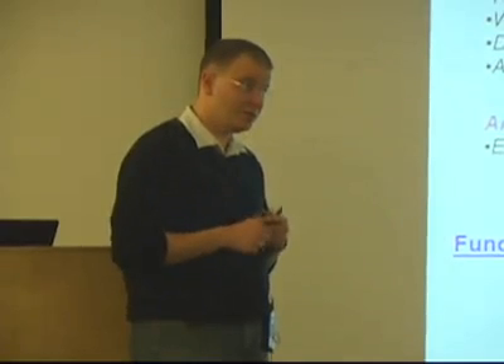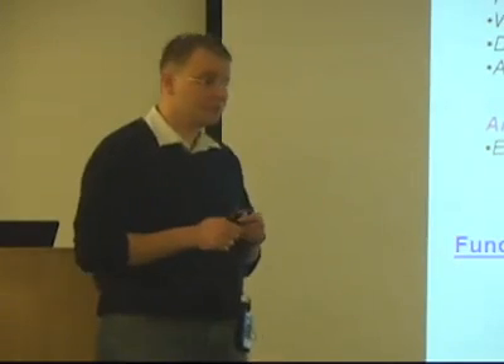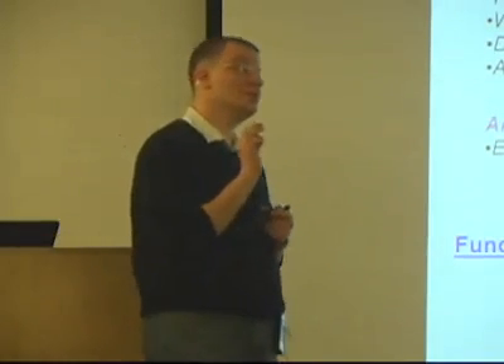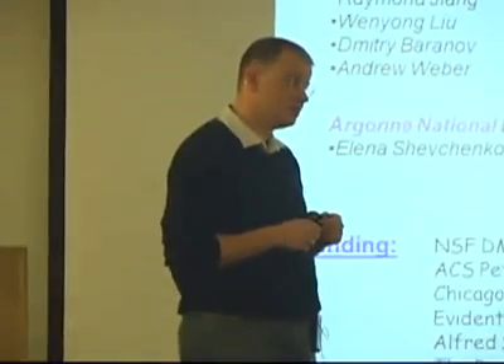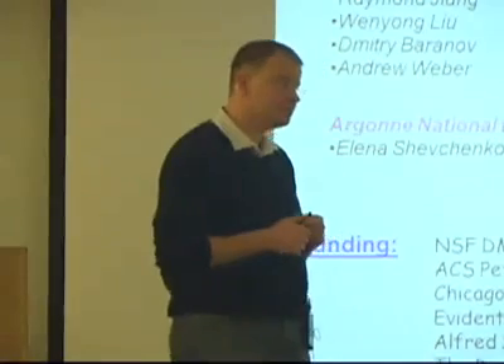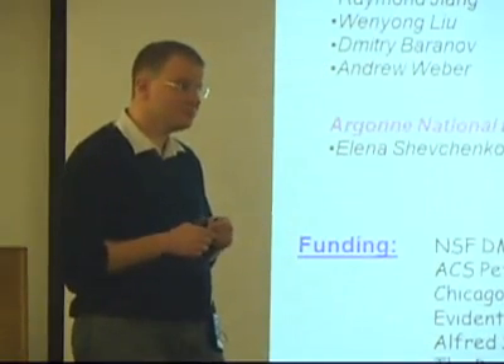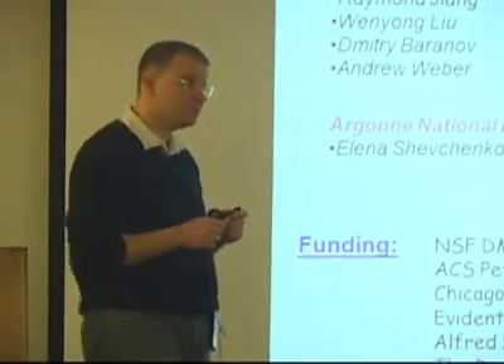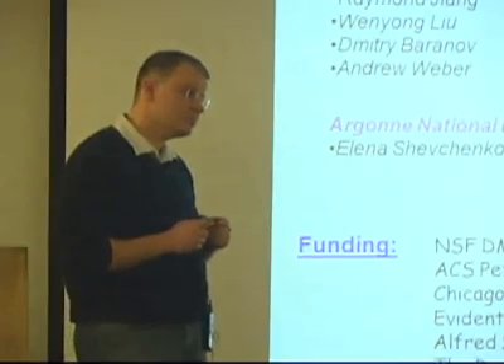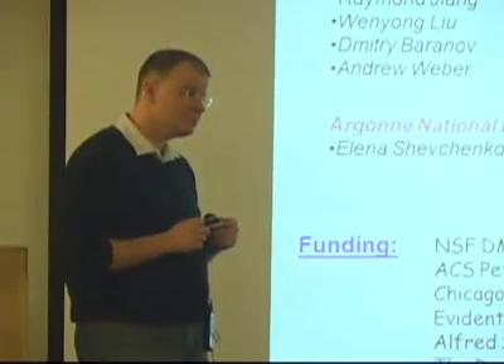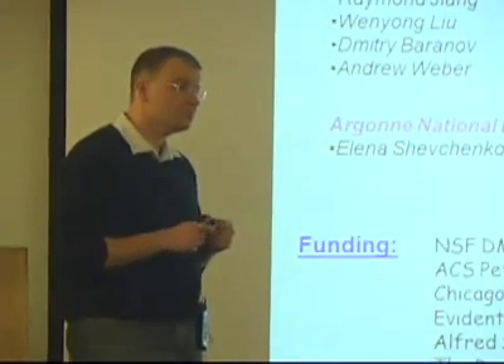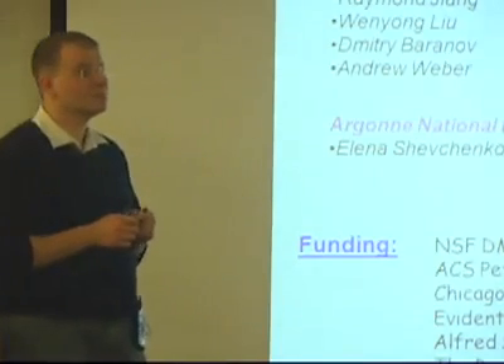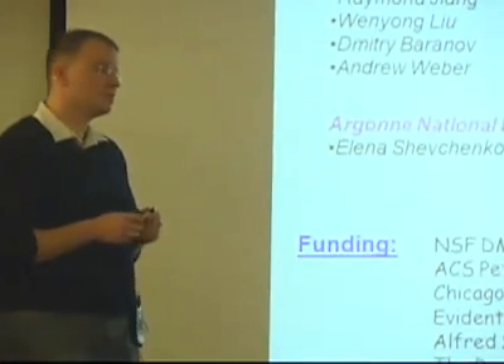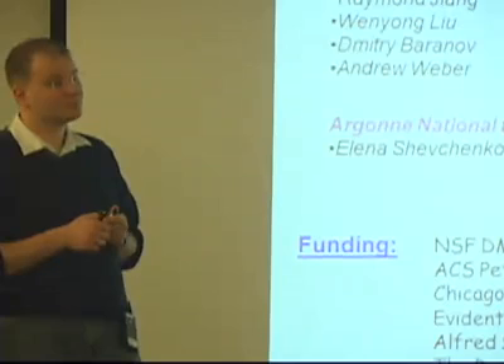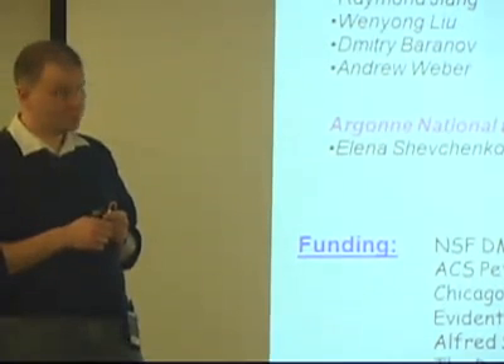Dark current is very good. Oh no, dark conductivity or carrier mobility in these structures. The carrier mobility we did not measure directly, but what makes the photoconductivity so efficient in this system, it's cadmium selenide, is that you have long-lived hole traps and you have a high photoconductive gain. We have photoconductive gains in the range of 100 to 2,000. So it's very large.